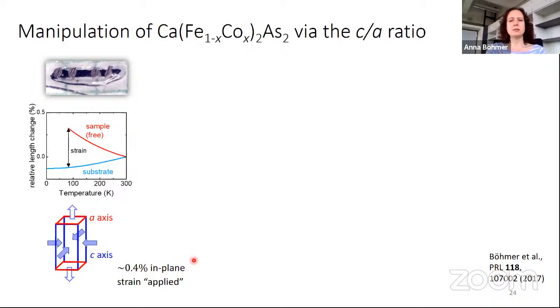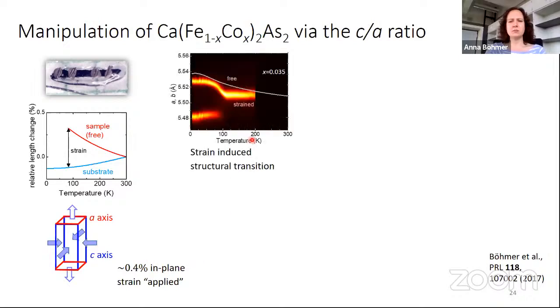And what happened? This is basically a sample length, but measured using X-ray diffraction. What we see is a transition as a function of temperature from a single peak to a double peak, or from a single lattice constant to a double lattice constant. What this means is there was a structural phase transition. Actually here, this was a square and now it's a rectangular lattice. That's what we see here.